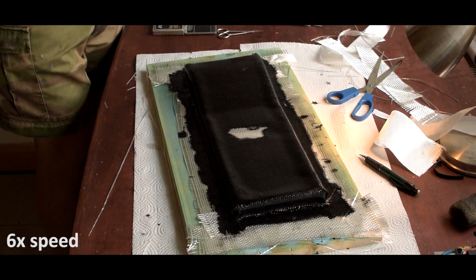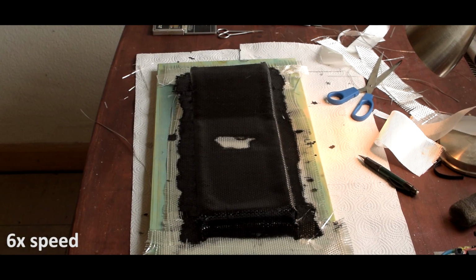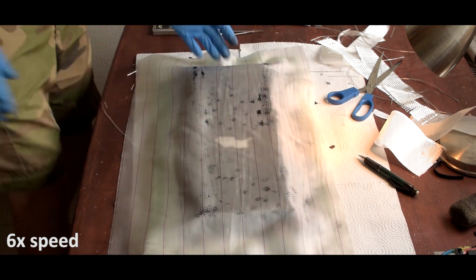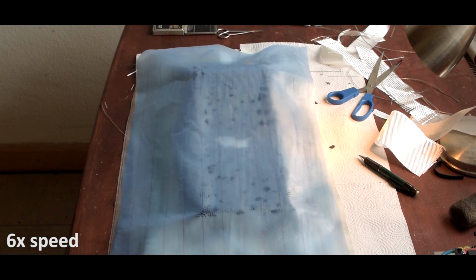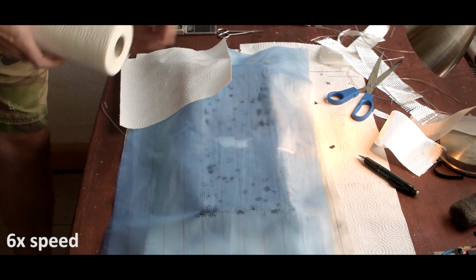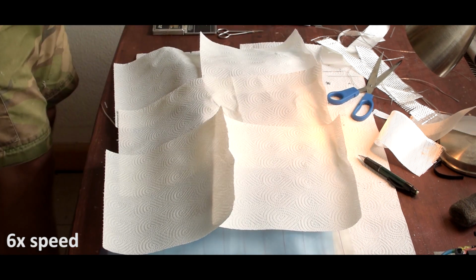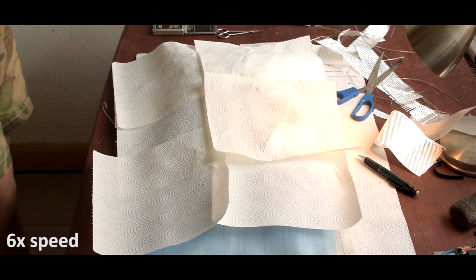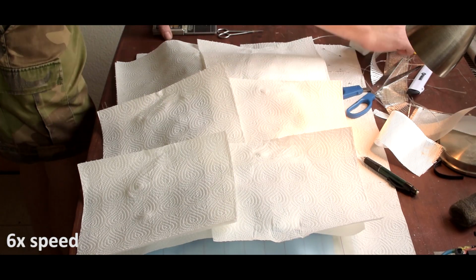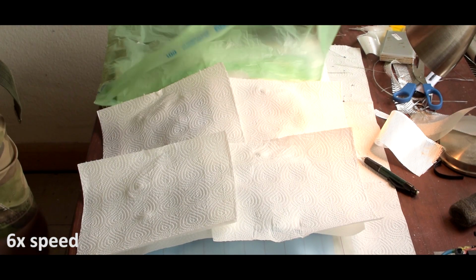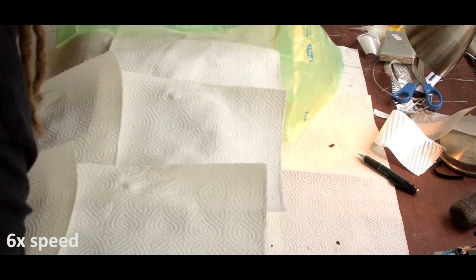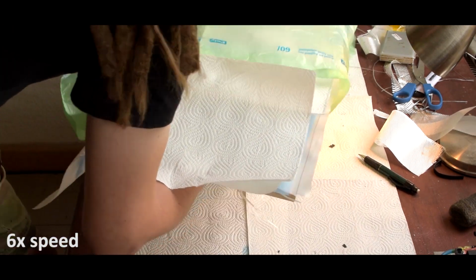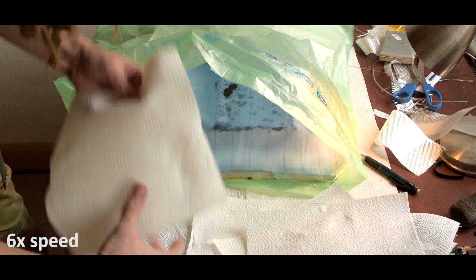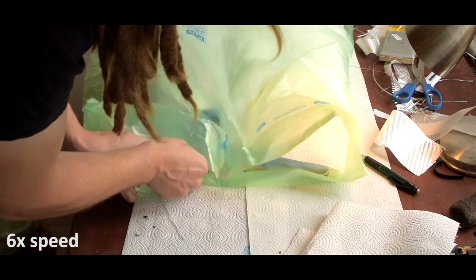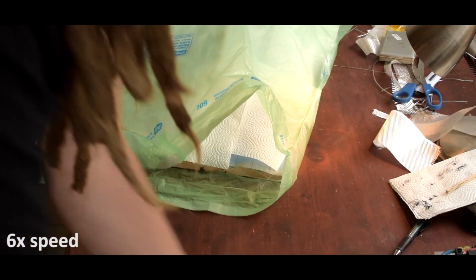So now, close to the finish, we add a layer of peel ply followed by a layer of perforated release film and some paper towels. Next time I add them after the mold is in the bag. The peel ply is like a fine net that does not stick to the resin. It gives your part a nice structured surface and can be released after the resin has cured. The release film and its holes allow the excess resin to be soaked up by the paper towels. This allows for a high percentage of fibers in your finished part, held together by a minimum amount of resin.